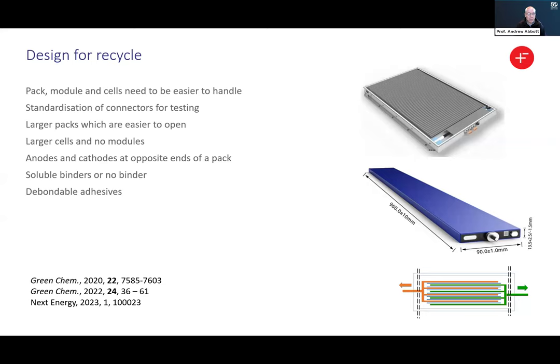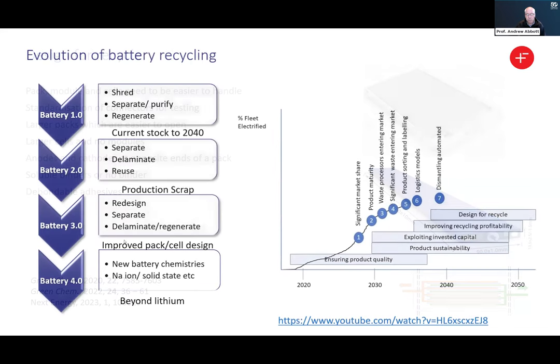We've also just started a project using debondable adhesives, where if you physically can't get away from using an adhesive, what you can do is put a trigger in there, which can be activated by light or heat, that actually debonds the polymer at end of life. And there are three references at the bottom of this slide to both debondable adhesives, but also the use of new battery designs that enable simpler battery separation and purification.